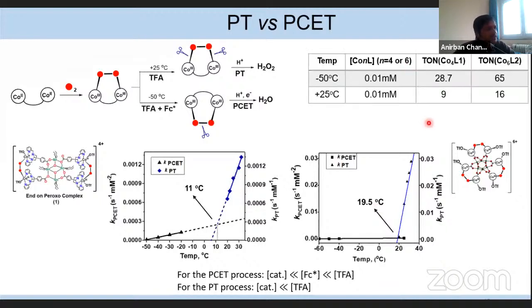However, when I determined the turnover number, I found that the hexanuclear cobalt complex is more efficient at both minus 50 degree and 25 degree centigrade, with turnover values 65 and 16, whereas for the tetranuclear cobalt complex, the turnover number is not that much compared to the hexanuclear species.